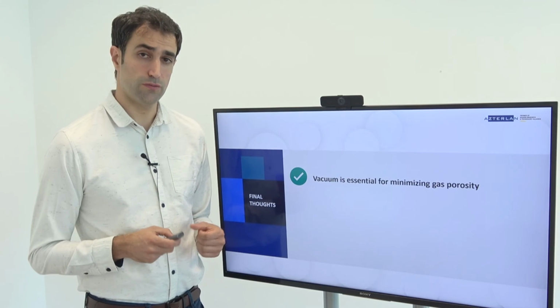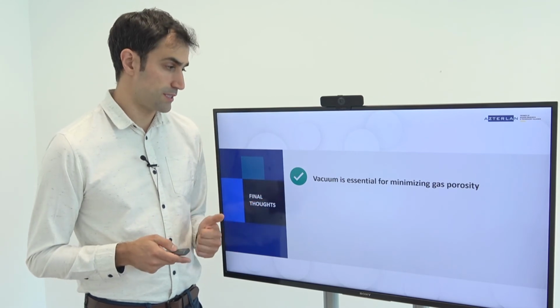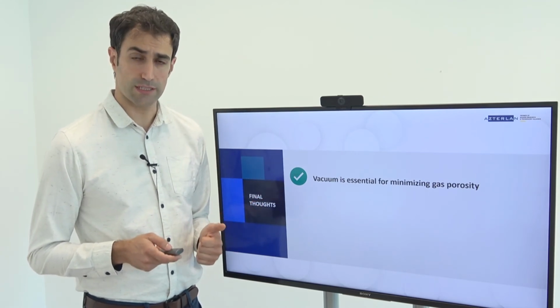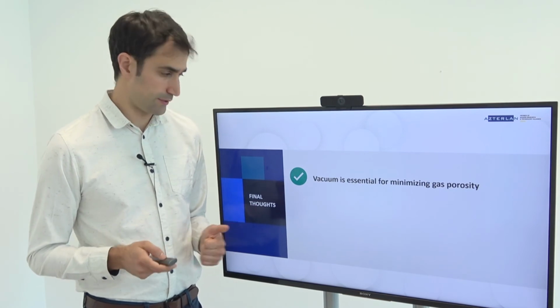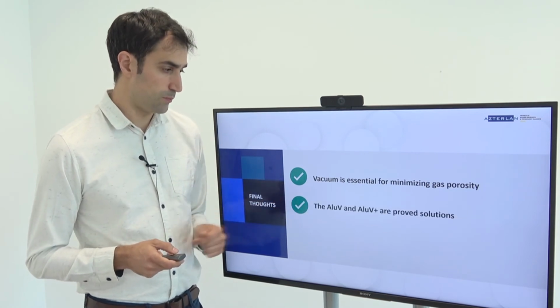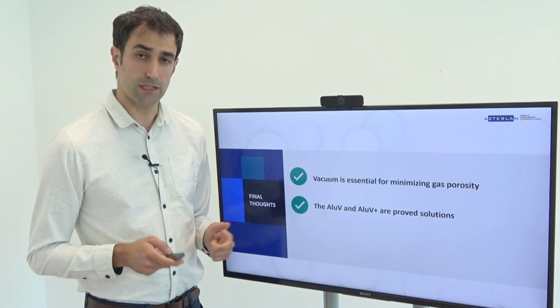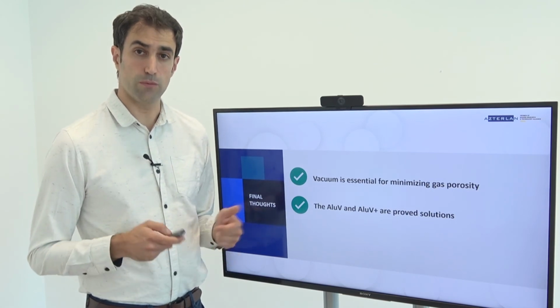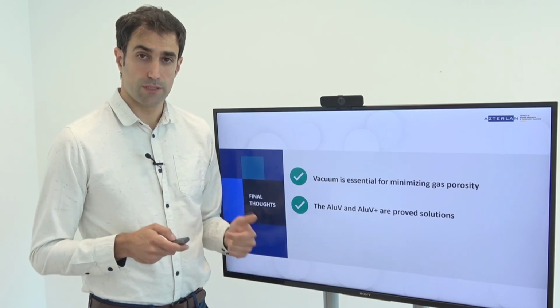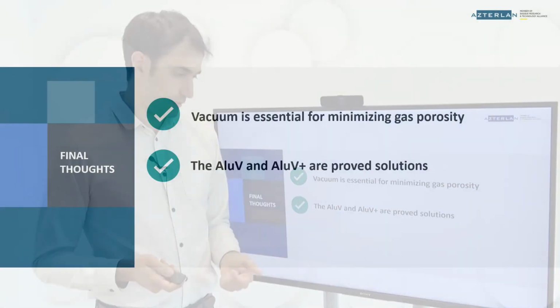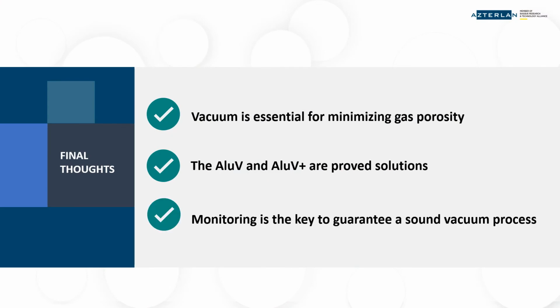So, pointing out some of the learnings: first, vacuum is essential for minimizing gas porosity as long as it is carried out correctly, without leaks. The ALU-V and ALU-V Plus are proven solutions. At Azterlan we developed the whole vacuum project, from the mold design to the setting up and finally the results analysis. Third, monitoring is the key to guarantee a sound vacuum process. Airflow and vacuum pressure are critical variables, and airflow can shed light on molds where we cannot have a measure of vacuum inside the cavity.